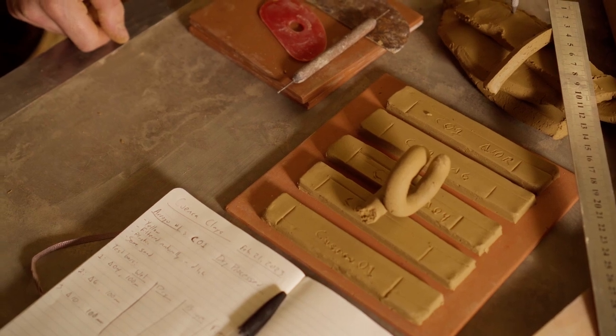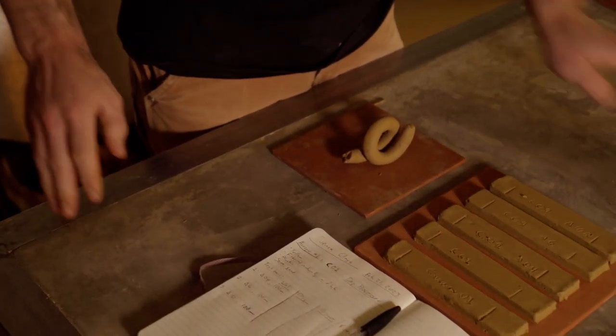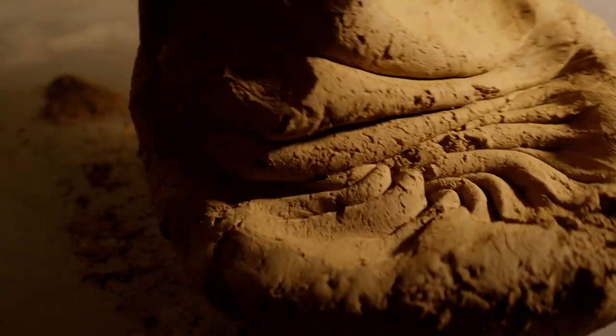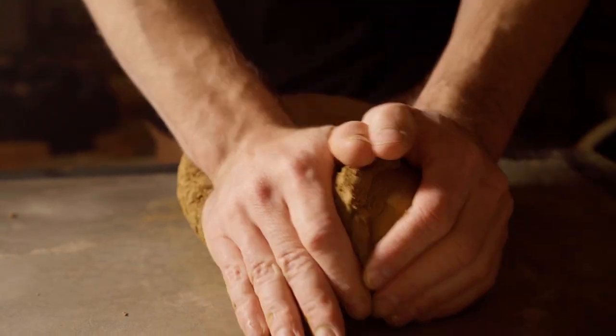If I suspect the clay is a low fire clay and will melt at cone 10, I might choose a common low fire temperature instead, like cone 1. Then I let these dry completely. When they're bone dry, I'll measure them and note how much they shrank during drying in my notebook. This number tells me how suitable the clay might be for more difficult shapes. A clay that shrinks a lot from wet to bone dry will require more care in making and drying to avoid cracking. Typically there is a direct relationship between how plastic a clay is and how much it shrinks, because smaller clay particles absorb more water. A sandy clay will shrink less because the sand isn't absorbing any water.